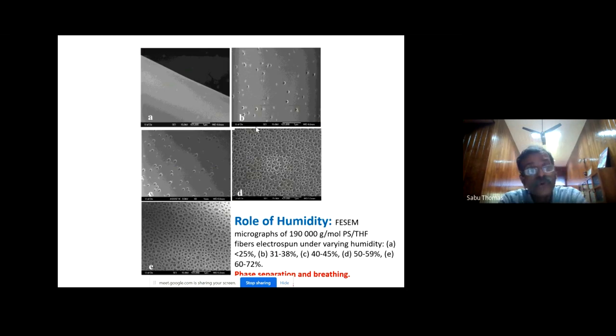Let me also say something about humidity. Dear friends, colleagues, students, when you do electrospinning, you all have to control one important parameter, the humidity of the electrospinning chamber. Look at this. This is electrospinning of a polymer with less than 25% humidity in the chamber. You don't see any hole on the nanofiber. But when you increase the moisture content in the electrospinning chamber, you will see a large number of holes on the spun fiber. What's the mechanism of this? Basically, phase separation and breath figures.